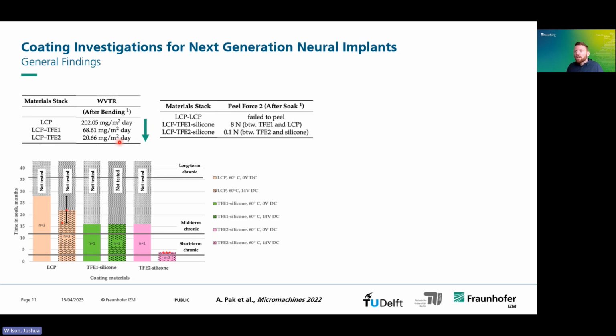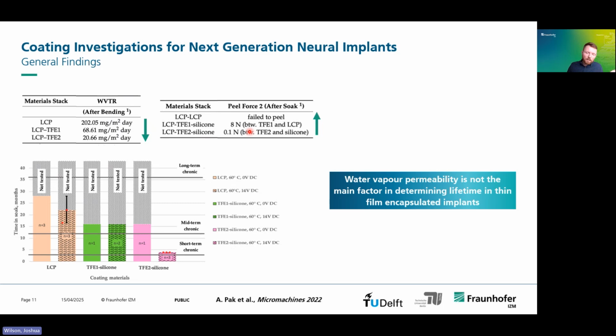Okay, easy. Another thing we investigated is the adhesion of these materials to the substrate. And it's the same material, same table basically. And what we see is the opposite trend. Now, when we tested our test structures in a long-term soak test, so we soak them in saline solution for months and years, and we raise the temperature in order to accelerate the degradation process, what we saw was that the devices that survived the longest were the ones that had the best adhesion to the substrate. So what can we conclude here? The water vapor permeability isn't the main factor determining the lifetime of these devices. The key is the adhesion, and I will try and hammer this home throughout the presentation.